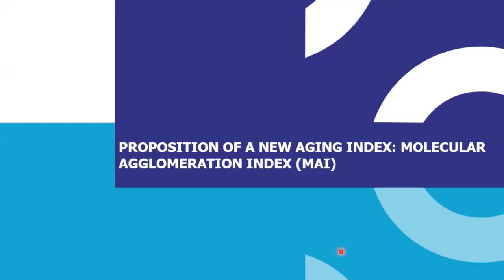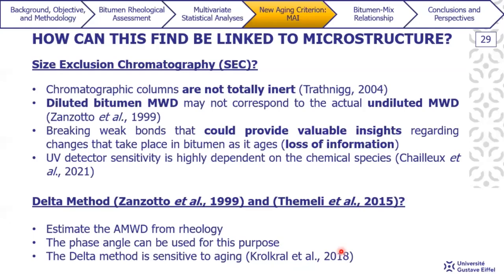And now I'm going to present the proposition of this new age index, molecular agglomeration index, or MAI. So our question was, how could this finding be linked to microstructure? In the literature, we can see that a way to determine the molecular weight distribution of a material could be using size exclusion chromatography, or SEC. But this procedure has some limitations that can be found in the literature.